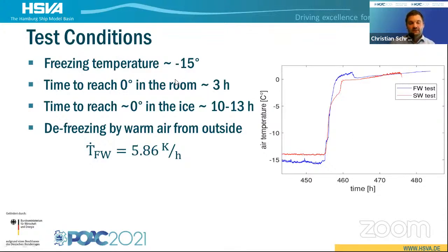We could reach, let's say, 0 degrees in the room after about 3 hours after we activated the ventilators, and after about 10 to 13 hours, let's say, the core temperature of the ice was in the region of 0 degrees, so at melting point, and the maximum forces could be measured.